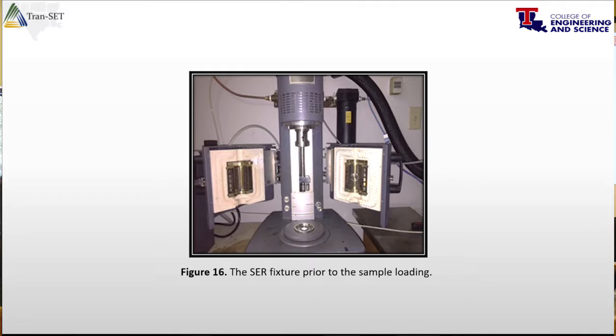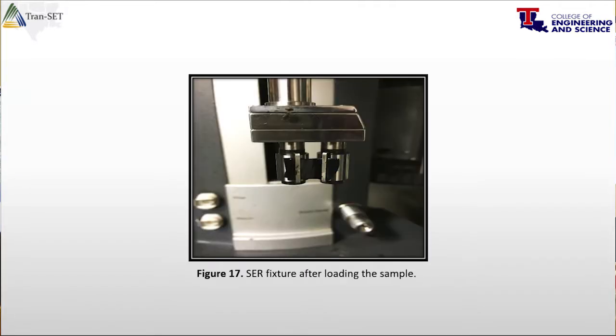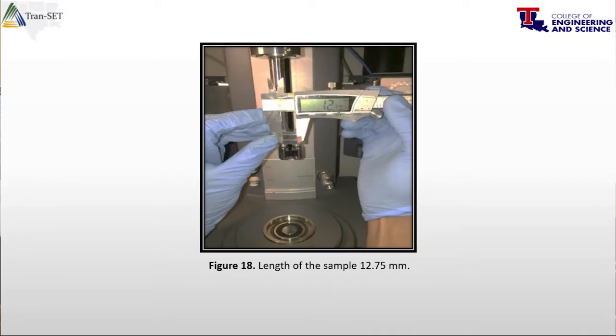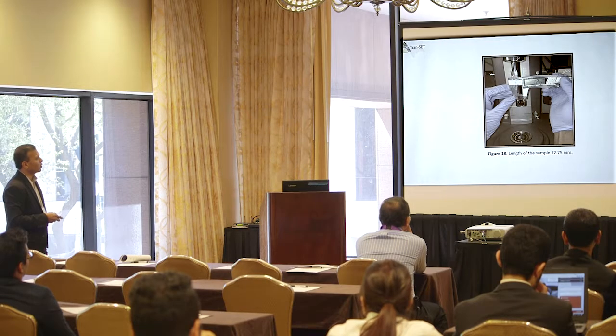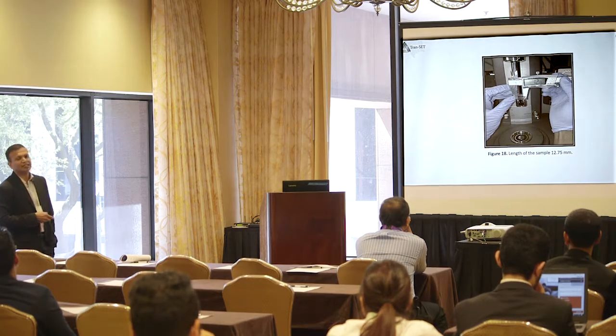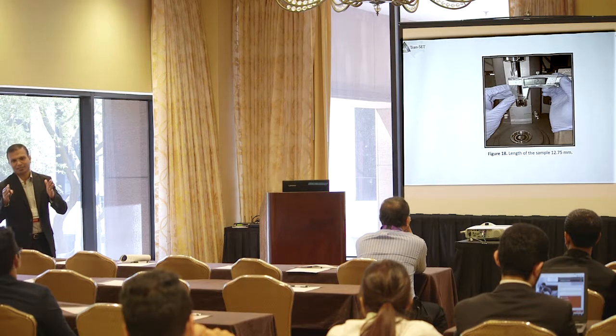You connect it to this one, and then you connect this shaft, and you have two drums here, and those two drums rotate, as you realize when you see the sample placed. You see that there are two drums. You place the sample here, and you put the staple here, and then you just plug in the staple here and here. So this height is always fixed. And you can see the length of the sample, 12.75 millimeter. No matter how long you cut, the sample length remains the distance between the two staples.